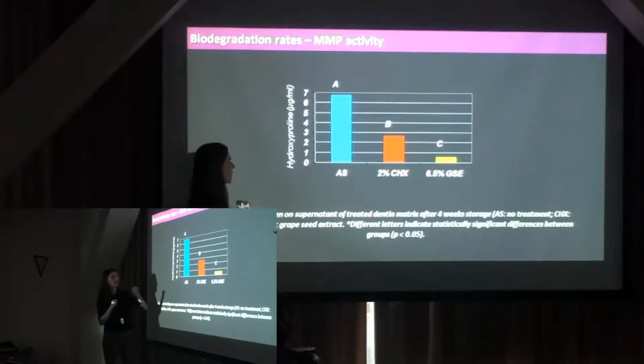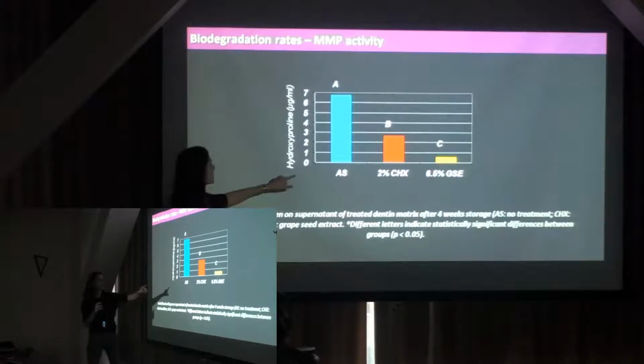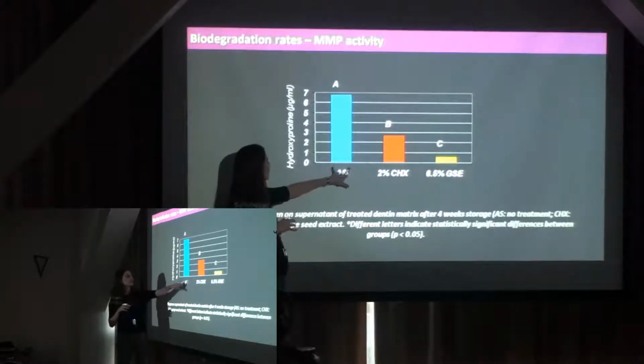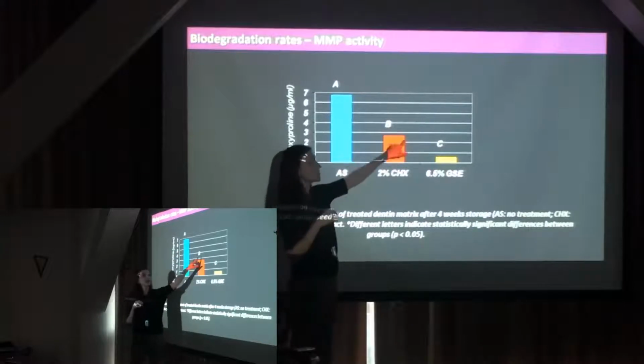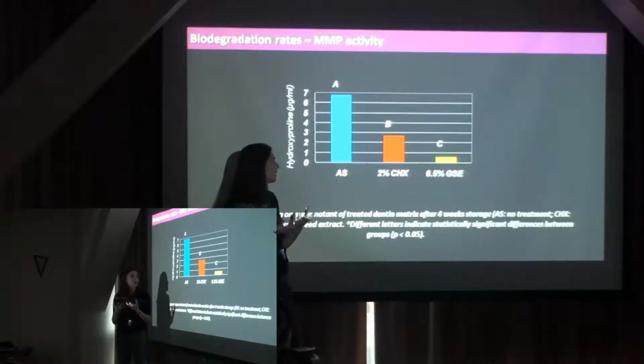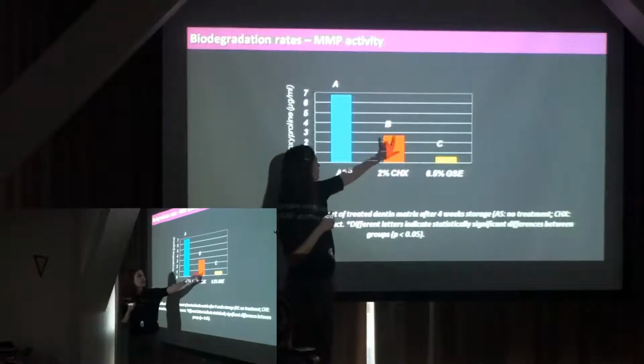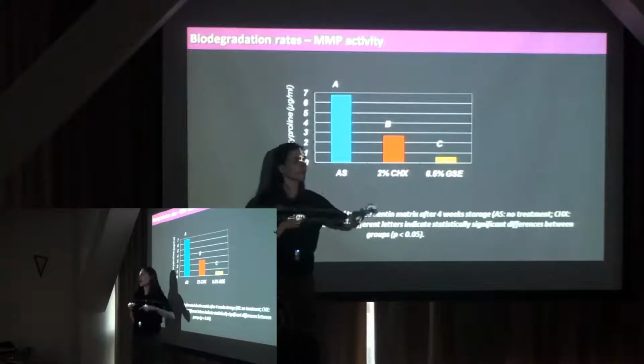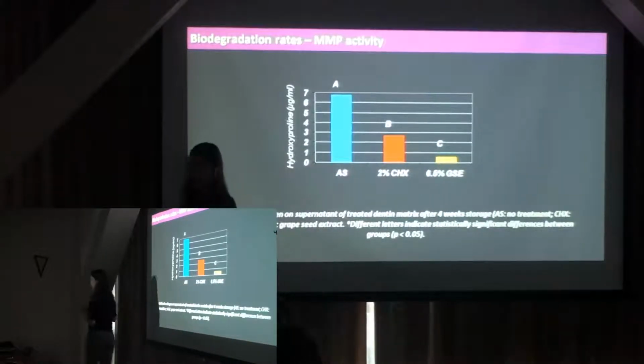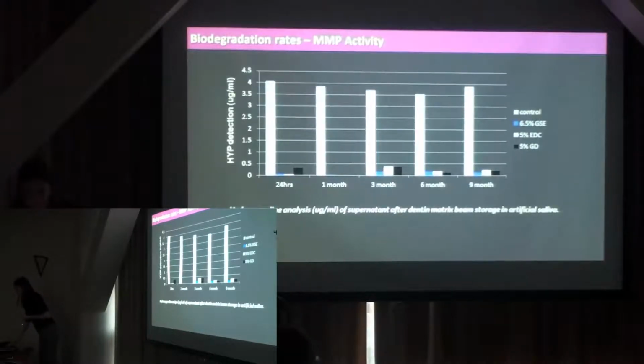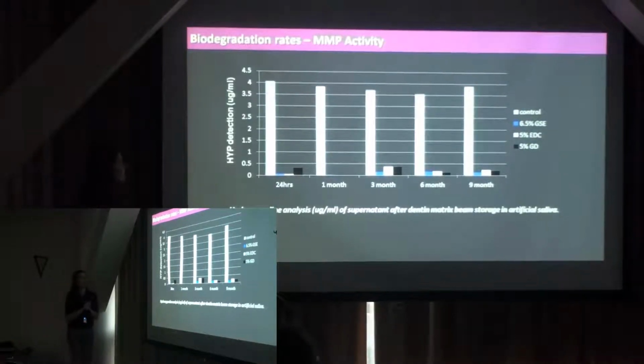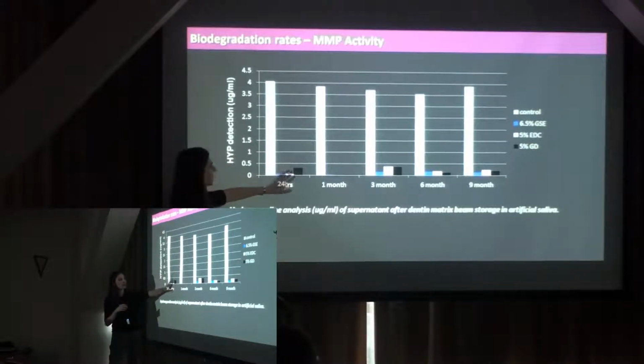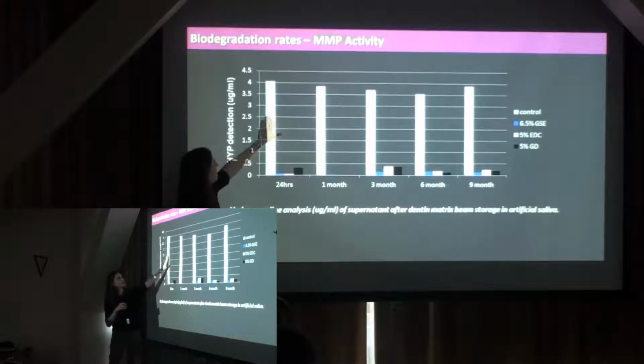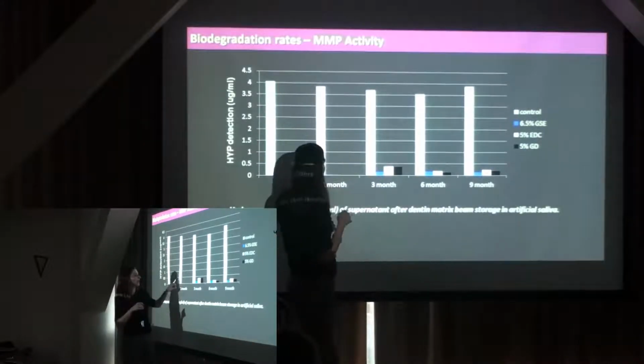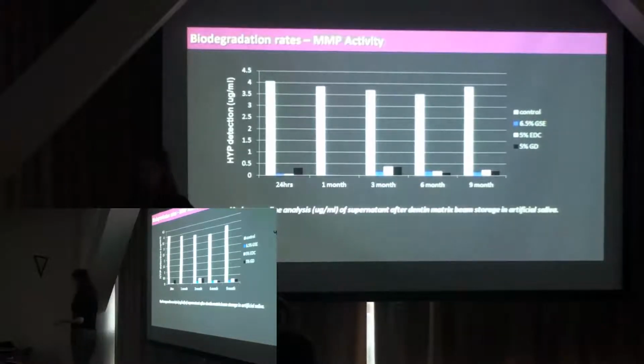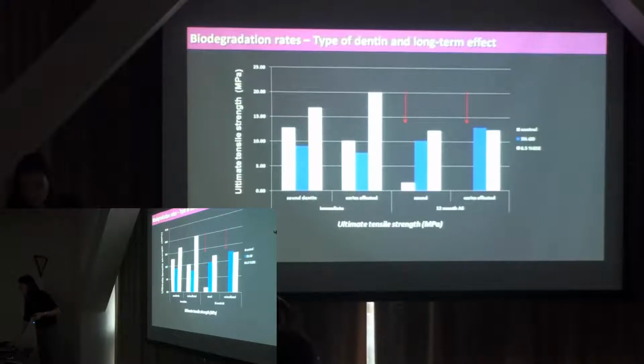So this is an example of materials that were left, I think, for 4 weeks. In the water of the control beams, we get a lot of hydroxyproline. Chlorhexidine has been used as a well-known MMP inhibitor, and we see a great decrease, but the grapeseed extract was 4 times better than even the chlorhexidine. And this is just another indirect method to evaluate MMPs in which we look at that content over a 9-month period, and we see the amount of degradation over the control and the stability of those matrices. There's really very little degradation going on after treatment.